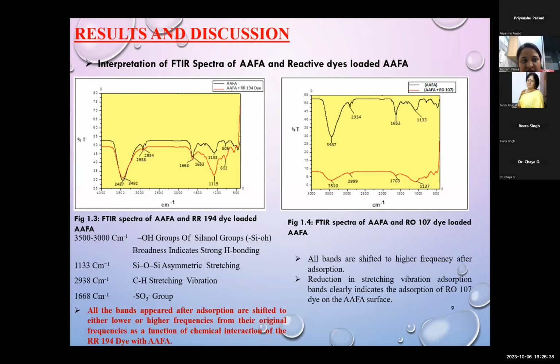Now, results and discussion. From the interpretation of FTIR spectra of alpha, meaning acid activated fly ash, and reactive dye loaded alpha, from the FTIR spectra for both dyes, we can say that all the bands appeared after the adsorption are shifted to either lower or higher frequencies from their original frequencies as a function of chemical interaction of the reactive red 194 dye with alpha. Here, the black line shows the raw fly ash alpha and the red line represents the dye loaded fly ash.